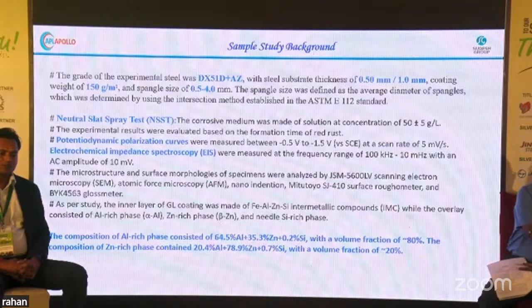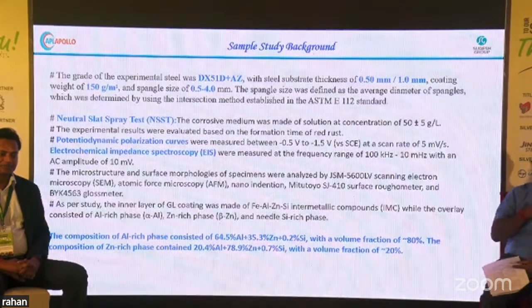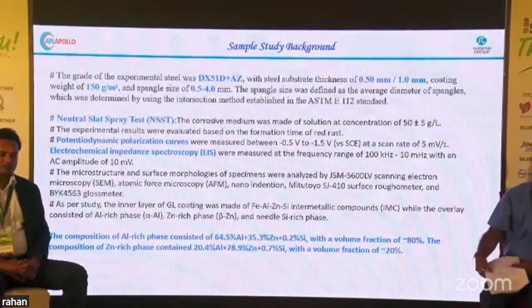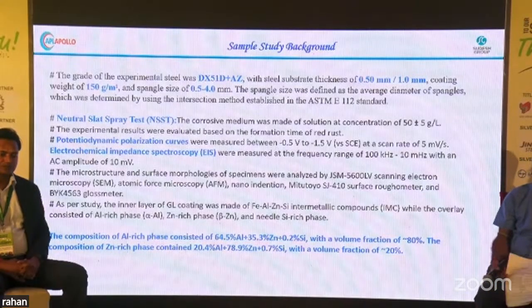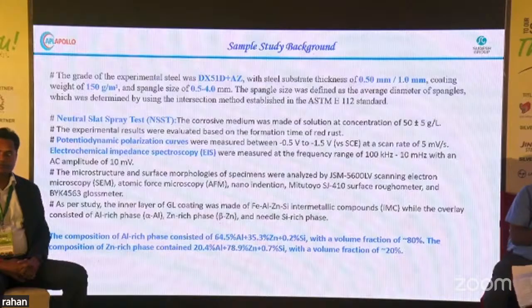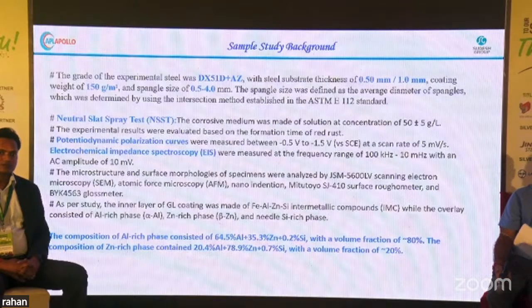And then corrosion we did in the normal salt spray test with a salt concentration of 5% at 35 degrees Celsius temperature, and we did validation by different methods like potentiodynamic polarization or electrochemical impedance. So some of this study is from research papers and some was done by us.